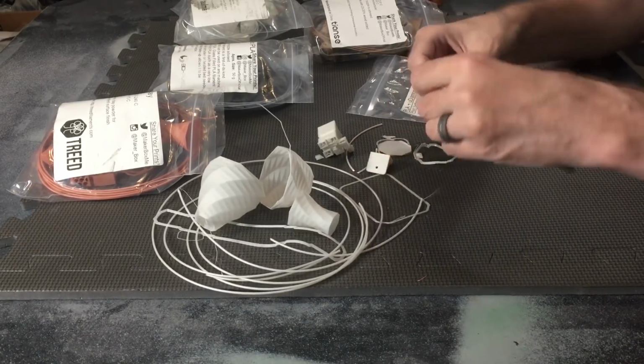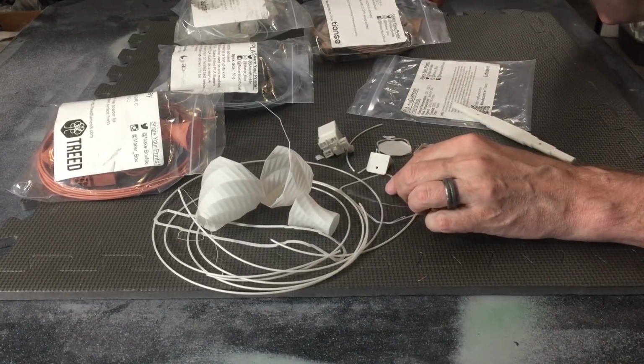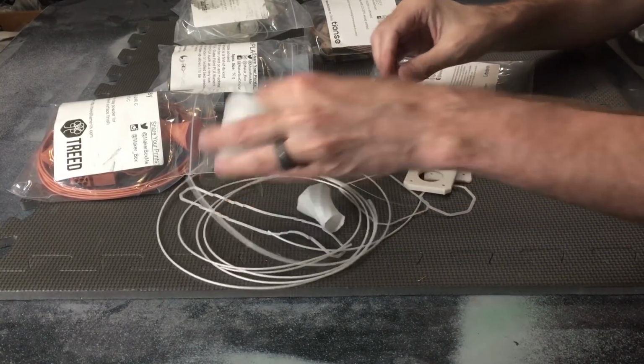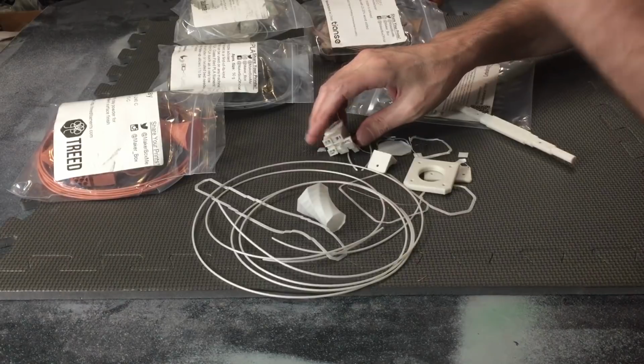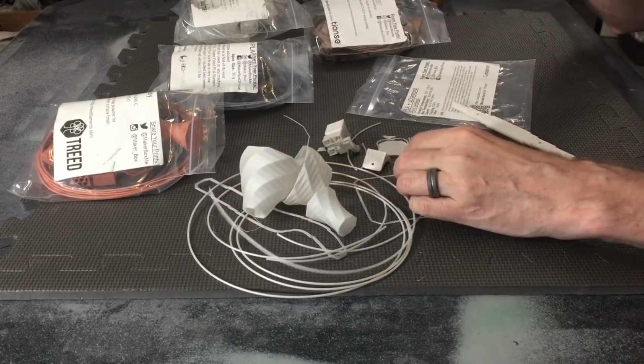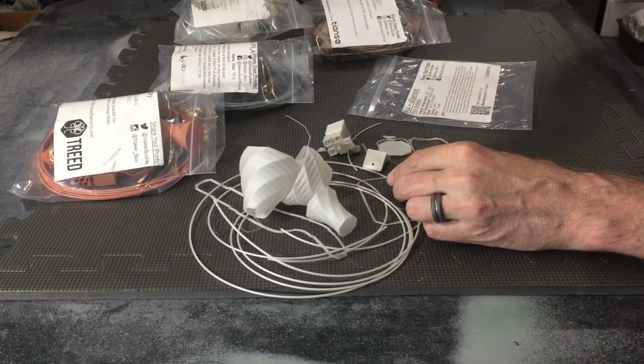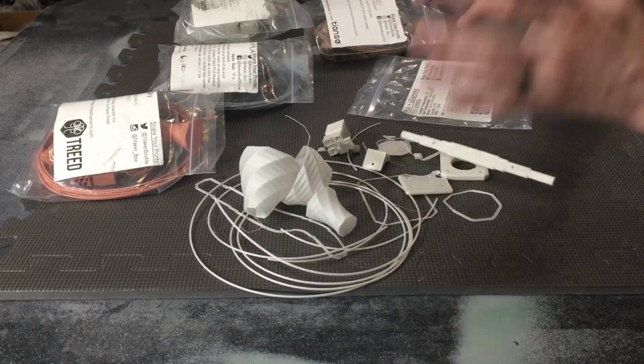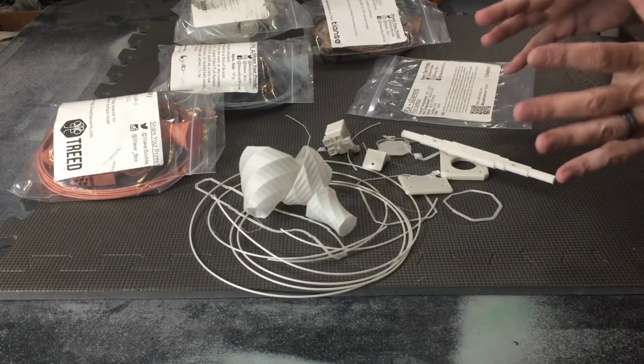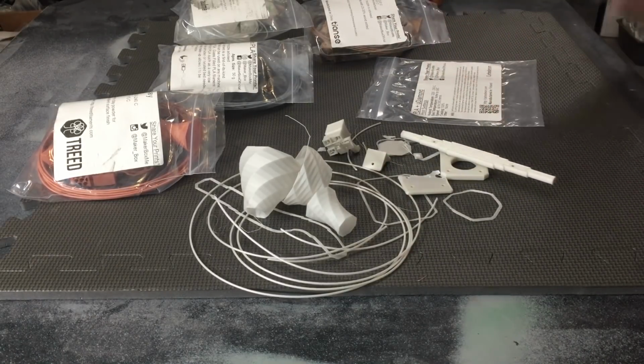So these printer parts were printed on the BuildTak with the Magic Goo, and these are printed on the sanded acrylic. These stuck too well. These stuck okay. This didn't stick so good on the edges. So a lot of parameter changes just to get the PLA plus U diamond to print.